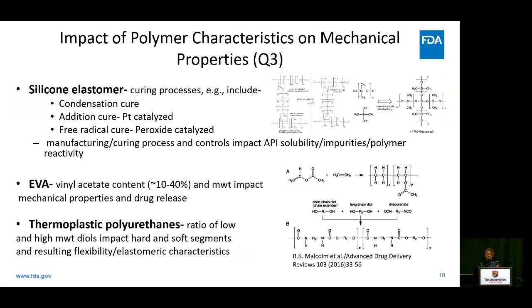As I've stressed previously, it is really critical to know that the polymer characteristics have a lot of impact on the mechanical properties of the final drug product. Such as for silicone elastomer, it's worth noting that the curing process, whether it's by condensation curing, addition curing, or free radical curing, may significantly impact the API solubility within the polymer, as well as the presence of residual monomers or even byproducts or certain impurities, as well as may result in some reaction occurring between the API and the polymer.